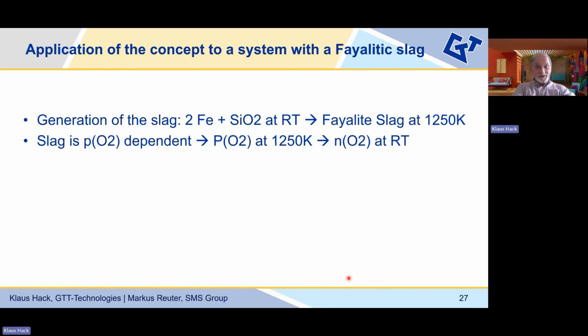That is one thing. The other thing is, depending on the conditions, and that is indicated in the second statement, conditions with respect to the oxygen partial pressure, we really need to figure out how much oxygen is actually contained in the system and how does that affect the actual phases which are stable at this high temperature, 1250 K. So what we have to do now is to figure out from those conditions in the first two statements, how can we apply Szargut for the reference state solid or liquid, and how can we apply the full works according to our general formula.